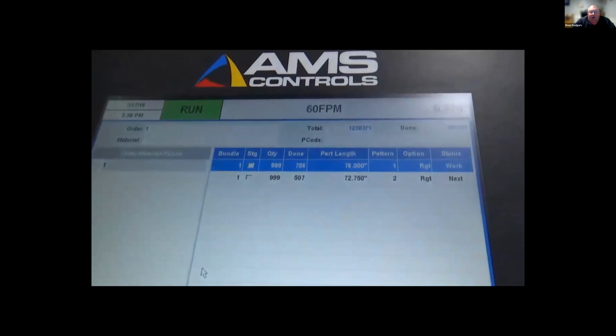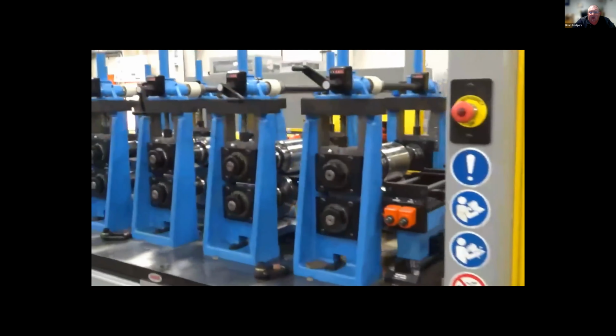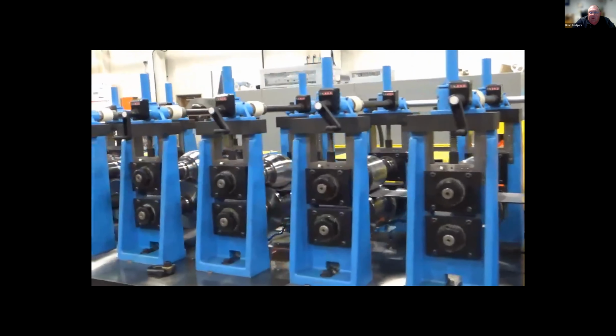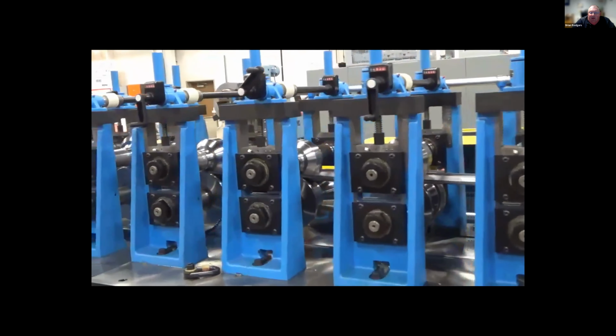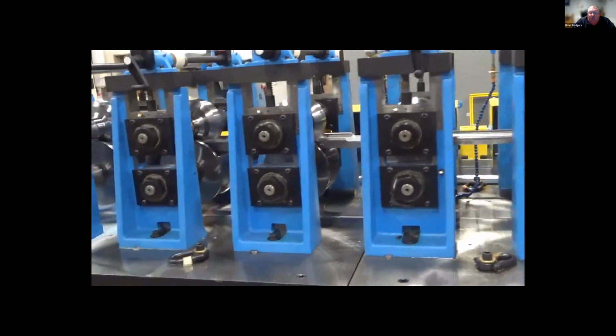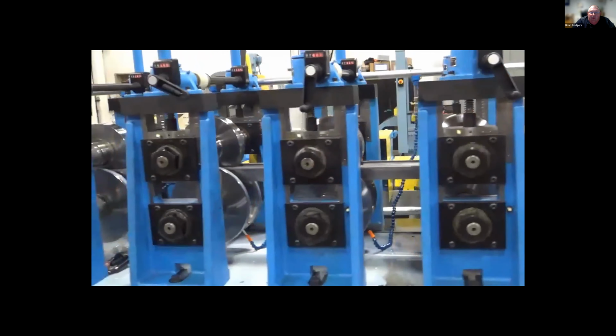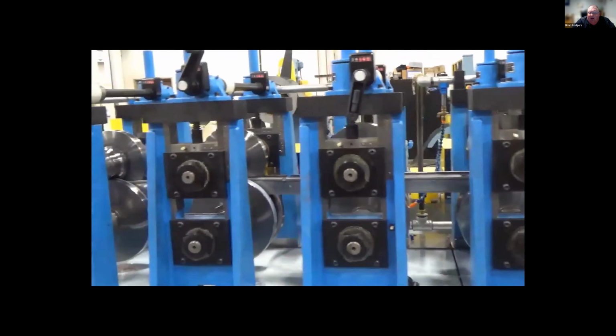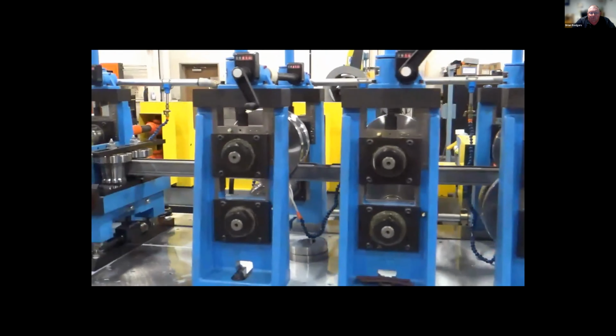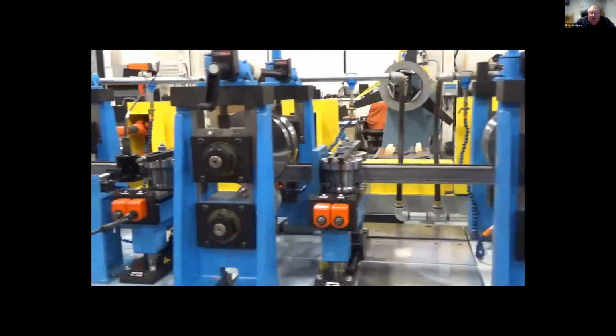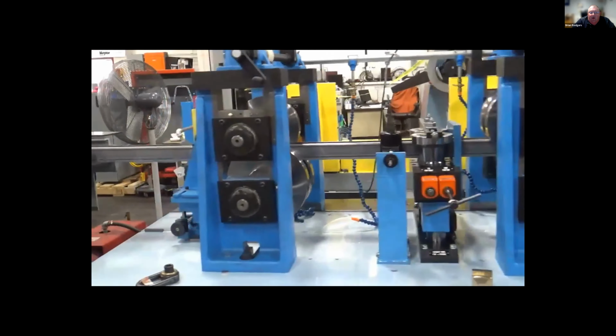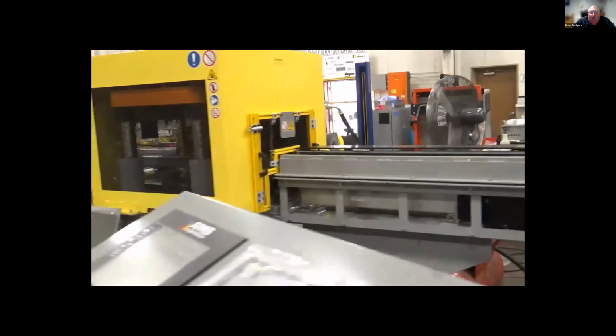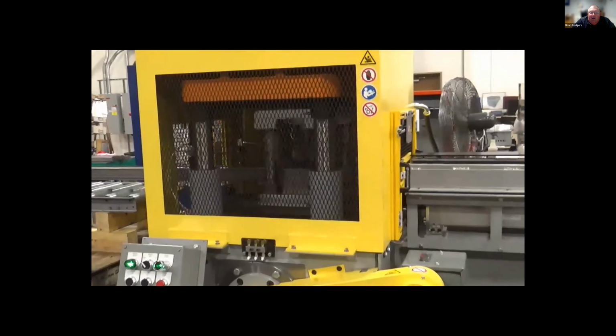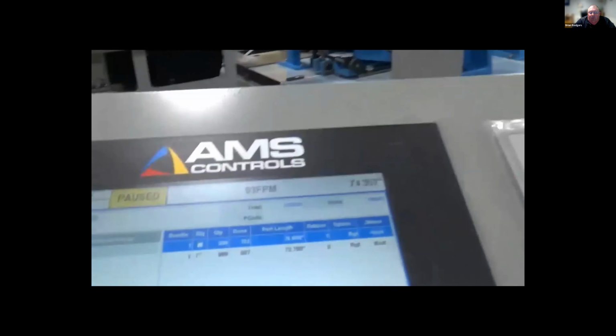Here's just the example showing this part is 72 inches long being ran, comes through, it goes through each one of the forming passes. As you can see on here, the edge of the material is actually taken away. So we started forming it in the middle and we started breaking it up. So all those features are in the part. And as it's coming through, it's bringing it up. There's one of those side passes I talked about earlier to help make sure that those legs are made correctly. And then we come into the cutoff operation where it will line up and it will cut through that feature, and it'll make sure that the part has the feature that's desired on the end of the part and on the exit end of the part in the correct spot.